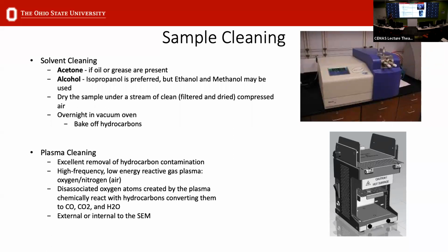One thing that you could still have on your sample is a thin layer of hydrocarbons. You won't see anything by eye, but once you put the electron beam on this area, you'll start to see this contamination build up on your surface, which can hinder your analysis and make your images not look very nice. A couple of options for that: you can bake your sample in an oven such as this one that we have here at CEMAS. You just heat up your sample to, depending on the position, 120 or 160 degrees C, I think, and that helps to get rid of those organics.